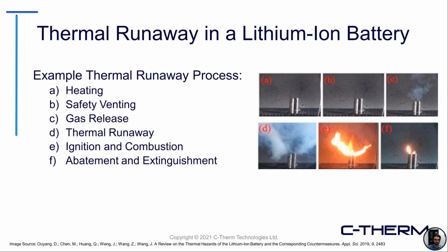Here is an example, thermal runaway in a lithium-ion battery, demonstrating the process. You can see that starting out at the top, image A, heating, there's no issues. B, there's the safety venting. C, gas release, but through some process here, there was not adequate release. And then throughout D, the thermal runaway event begins. And this leads to an ignition, combustion. You can view that as the destructive event. And then at a certain point, it will be self-extinguished, but now the battery is damaged.